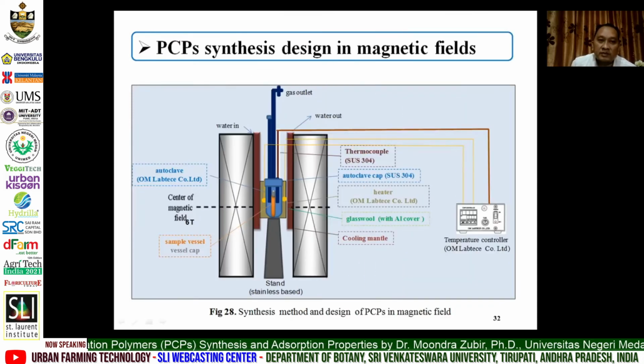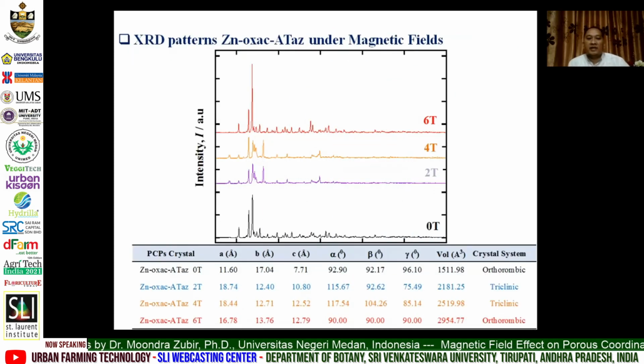The characterization is by XRD, and the pore properties are observed by nitrogen and carbon dioxide adsorption. And the same also, this is PCP synthesis under magnetic field. We synthesized at 0 Tesla, 2 Tesla, 4 Tesla, and also 6 Tesla. And this is the XRD patterns of Zn-oxac-ATaz under magnetic field. Similar with zinc oxide TAZ, between the 0 Tesla and 6 Tesla, it looks like no significant difference. So we consider that these two kinds of PCP, TAZ and ATAZ ligand, have a serious effect on the structure by magnetic field at low magnetic field, or 2 Tesla and 4 Tesla, lower than 6 Tesla, because the 6 Tesla magnetic field crystal is not significantly different from 0 Tesla.